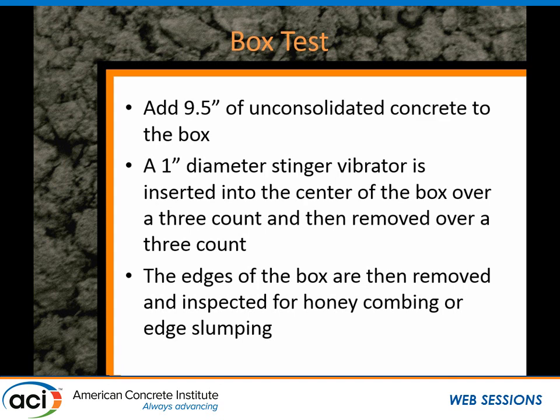We're going to take nine and a half inches of unconsolidated concrete and put it inside the box. We're going to take a one-inch diameter stinger vibrator. We've sized the vibrator, the RPMs, and the energy to match the amount of energy that a paver would typically put into the concrete with a typical vibrator spacing at a typical speed. You go three seconds into the concrete, three seconds out, in the very center.